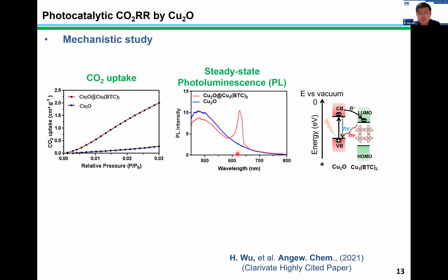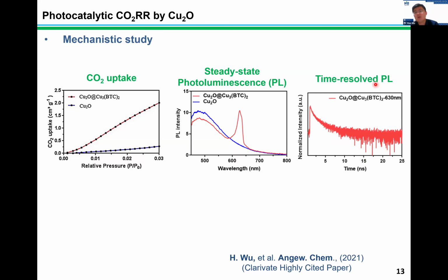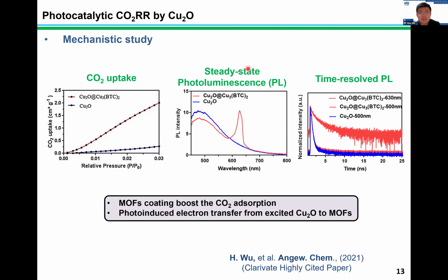To further prove that, we also did the time-resolved photoluminescence studies. We first monitor their emission signal at 630 nanometers. We found that, similar to the steady-state PL, only the copper-based MOF composite material shows a very obvious signal, but for the bare cuprous oxide, we can't detect its PL. And when we monitor their signals at 500 nanometers, we can see that both samples show signals but with negligible difference. So the time-resolved PL results agree well with the observation from the steady-state PL, and it suggests that there is photo-induced electron transfer from excited cuprous oxide to copper MOFs.